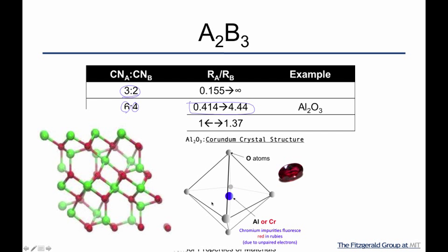But over here is a complete structure, and it's a little bit more difficult to see. One thing that you'll notice is that this is a Corundum structure, and it has a close packed direction, which you can kind of see here. There are layers of the 2 different elements tightly grouped, and then there's a bigger space, and then you have another set, and that's because the stacking that happens is the high density direction, which in Corundum is the 0001, if you were to use that kind of indexing.